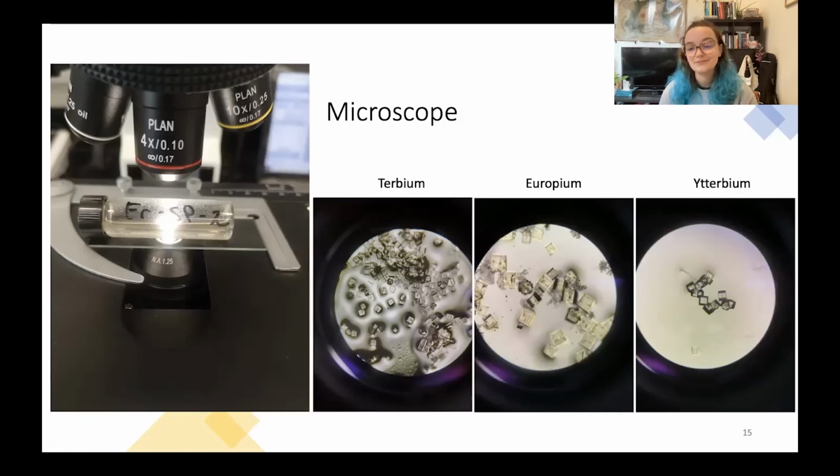Sorry, you can see a couple of images under the microscope. So these are right out of the oven, put them under a microscope to see what they would look like. And sure enough, we get small crystal cubes, clear cubes, which is what the original paper stated we should get. So it looks like we achieved to make a UPC-68.